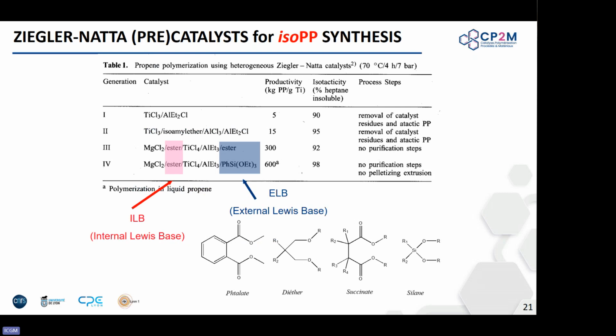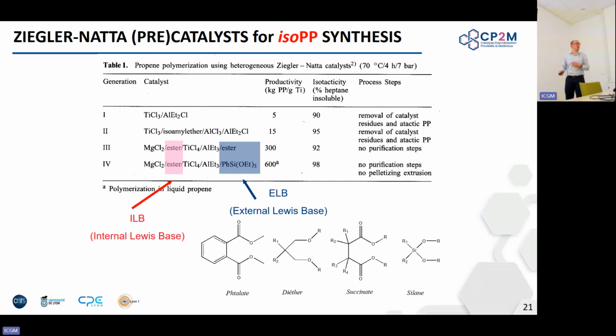And then you can get very fancy, especially if you want to design a pre-catalyst that upon alkylation and reduction will give you isotactic PP. If you want that, you need to add, like in the recipe, a little bit of internal bases. It's to tune the surface of the magnesium dichloride support. And then at the polymerization stage, you also need to add an external base, and this will tune the geometry of the active site to induce regioselectivity and stereoselectivity. So I gave you some examples. Internal bases are usually phthalates, and silanes for external Lewis bases. These are very standard strategies.